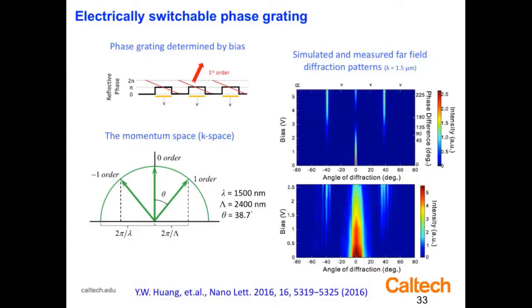As we change the voltage on this little transistor-like structure, the surface goes from one where all the antennas have the same phase, so we get specular reflection at 0 degrees, specular reflection at normal incidence. The specular refracted beam goes away and breaks into a plus one and a minus one order diffracted beam. Essentially, we've made a switchable diffraction grating. So now, by applying different voltages to the gates, I can make whatever phase relationship I want.